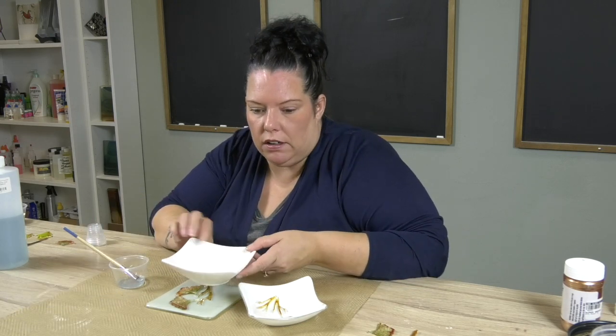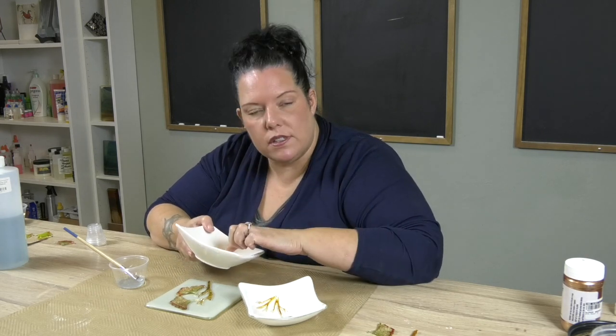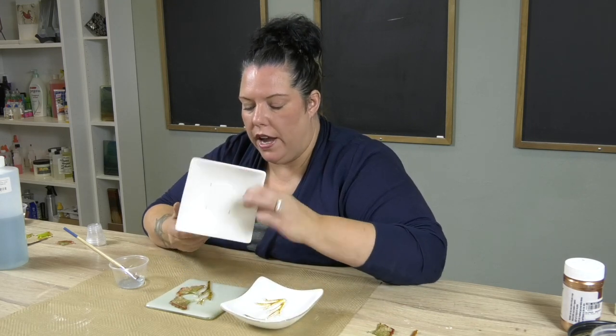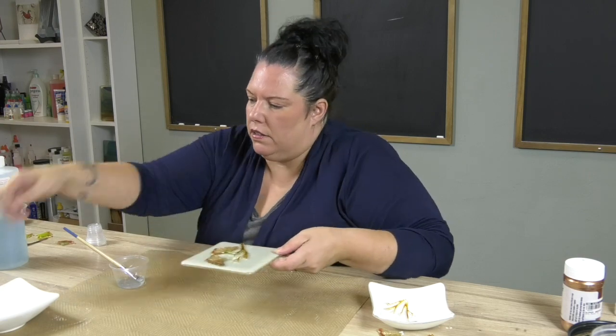This mold right here is very deep. It's about 2 inches deep, and I want to slump it all the way to the bottom to get that nice rounded bottom here. So yeah, that's it. Follow that schedule. And if it doesn't slump all the way, put it back in and slump it again. Hold it longer, okay? All you're gonna do, 5.5 inch glass.